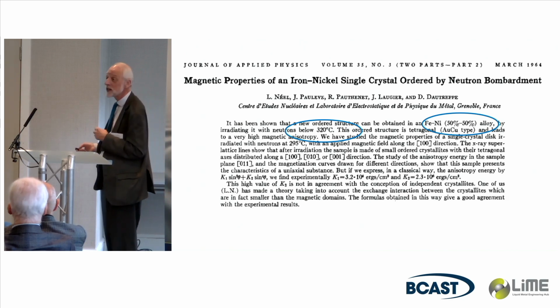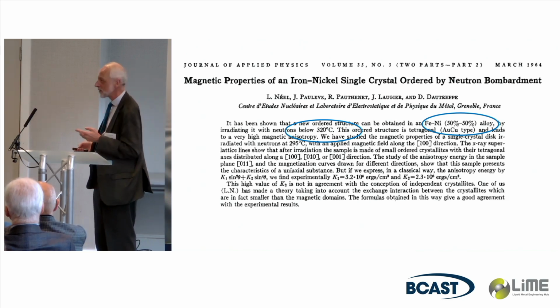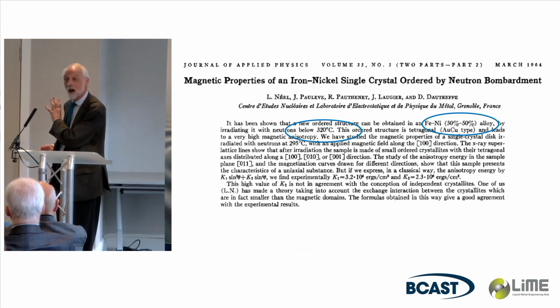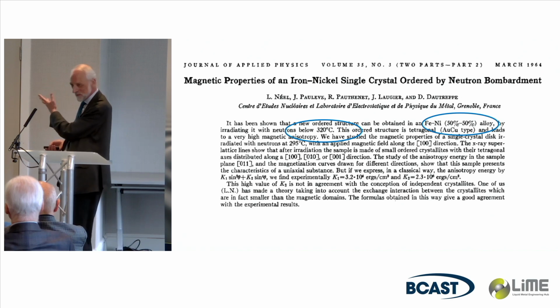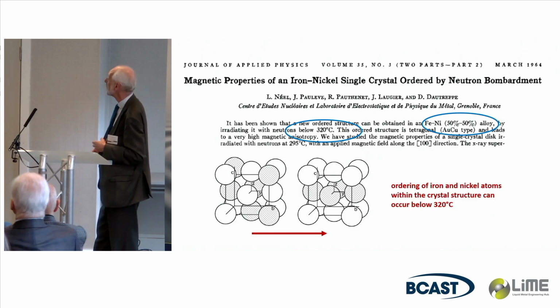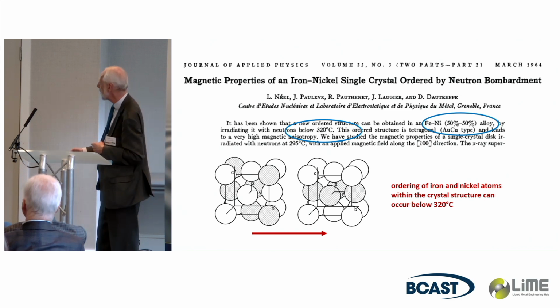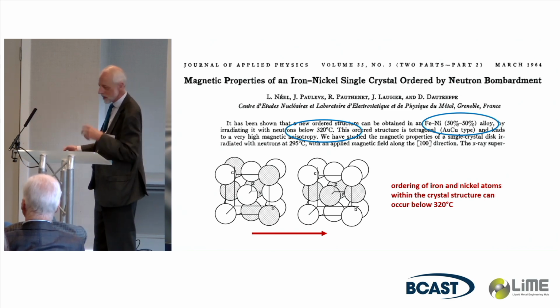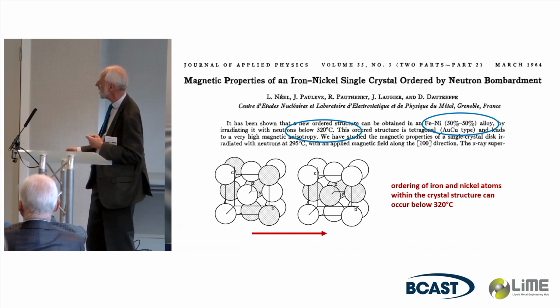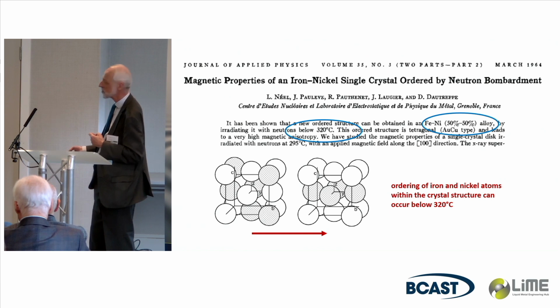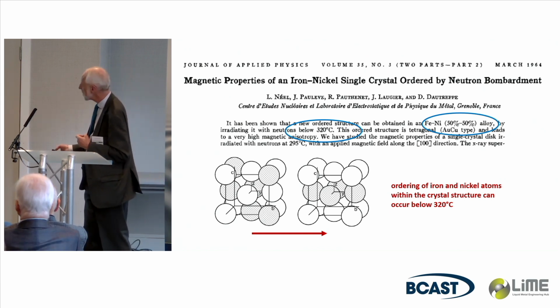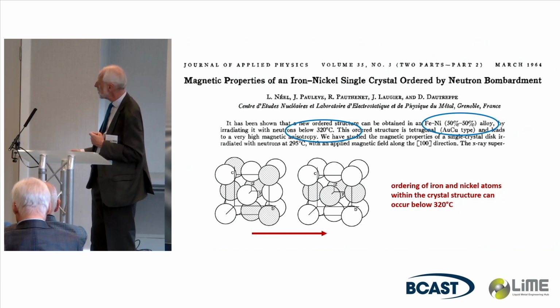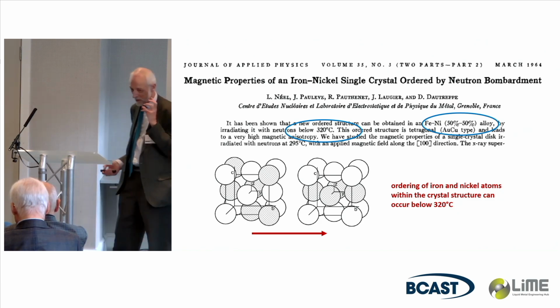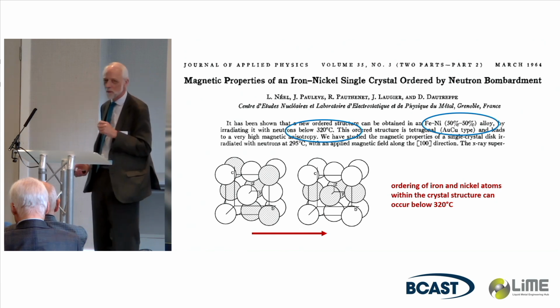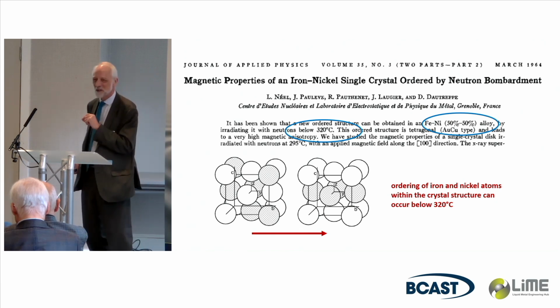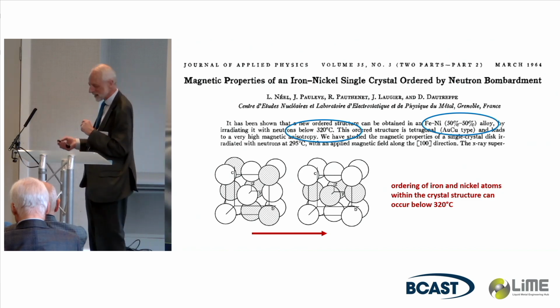And they went to neutron irradiation as a way of achieving that and made some progress. They expected that this would be a good high-performance permanent magnet material, but clearly it didn't become a commercial viable thing to do. This is the ordering. So the lighter and darker shading represent iron and nickel. They're meant to be randomly assigned on the sites on the left and ordered into this layered structure on the right. You've lost your cubic symmetry. The unit cell dimensions don't deviate much from the cube. The axial ratio in the ordered form is about 1.007. So it's very, very nearly cubic, but it's not technically got that symmetry.